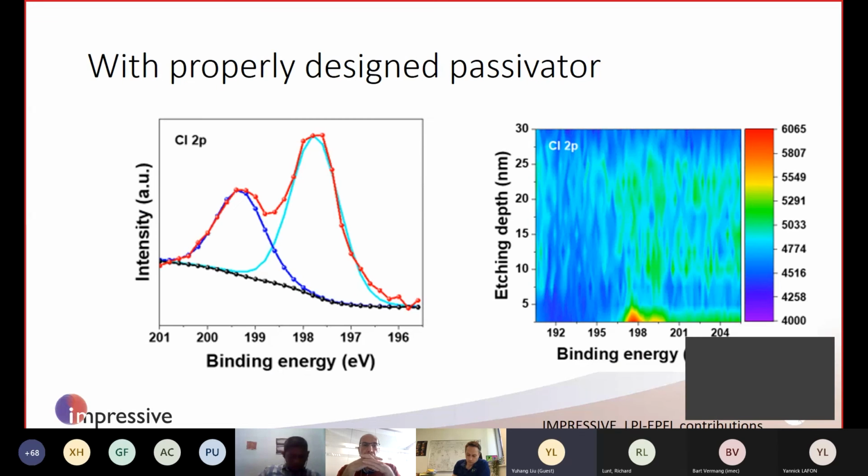As I also mentioned, with this MAPbBr3 perovskite, because of its polycrystalline nature and solution processing, surface defects are also one of the intensive problems causing poor efficiency of this kind of cell. So we introduced a newly developed surface passivation agent, neopentylammonium chloride, to apply on the surface of this MAPbBr3 perovskite.